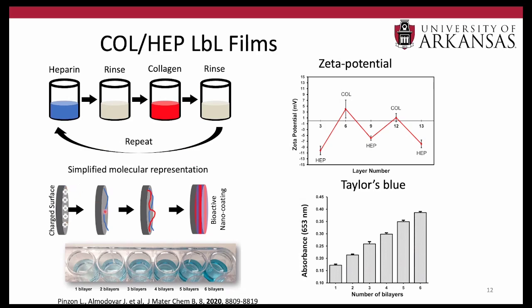And as we do that process, the polyelectrolytes get deposited on our surfaces due to the electrostatic interactions. I'll only show this slide for characterization, but we have done a very extensive chemical and physical characterization of these coatings, and we've demonstrated that they're quite stable with temperature. The coatings are in the nanometer range. Depending on the number of layers, but with the number of layers that we typically use, the coatings are about 70 nanometers or so.